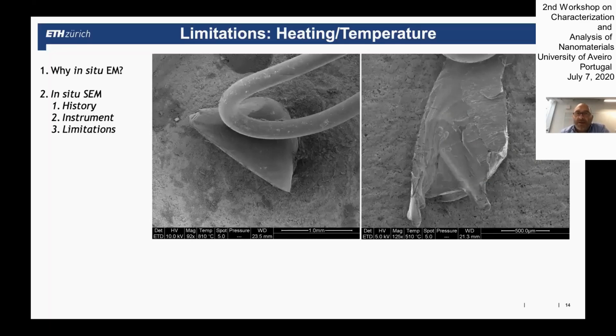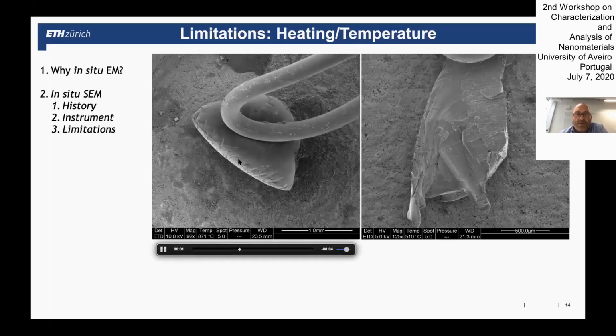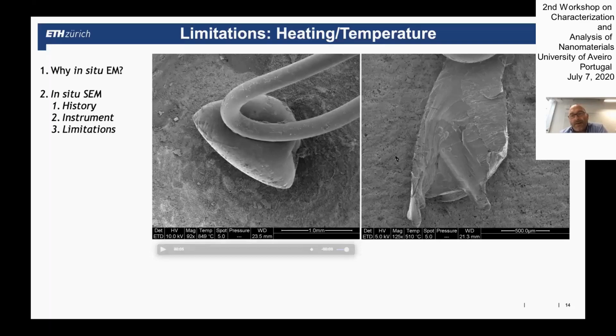That is not easy. So we usually have thermocouples that we attach as well as we can to our samples, but then it really depends on how well you can put your thermocouple onto your sample. And we did some experiments to estimate how accurate our temperature measurements are. I have here some videos where we heated up little pieces of aluminum and put them down onto the heater with some mechanical force, and we measured the melting temperature. You will see in this video that at one point it gets liquid, and we measured the temperature where it gets liquid, and then we mounted the thermocouple.